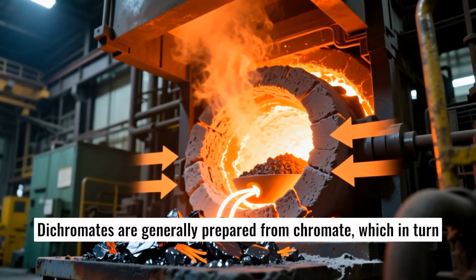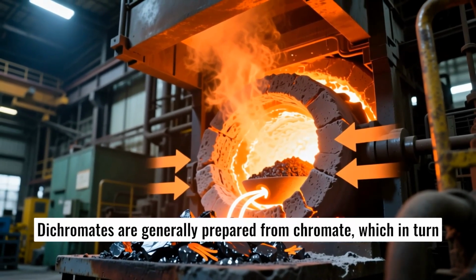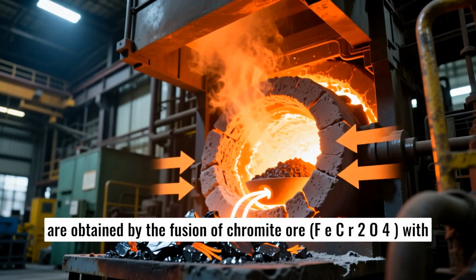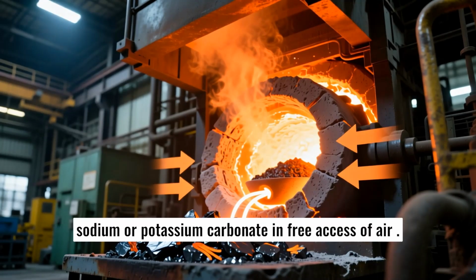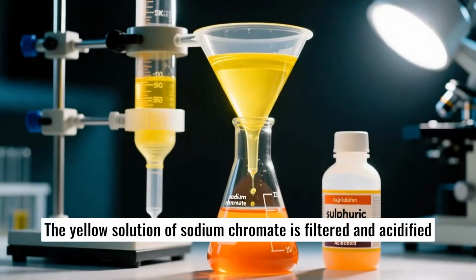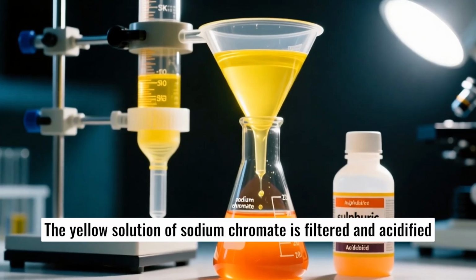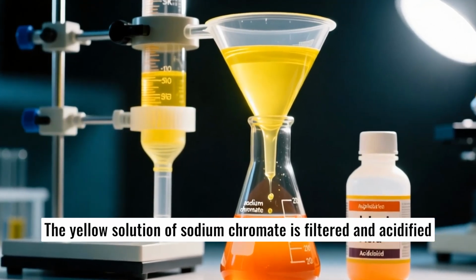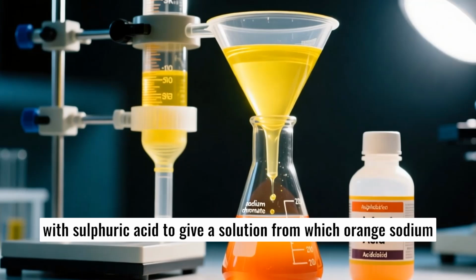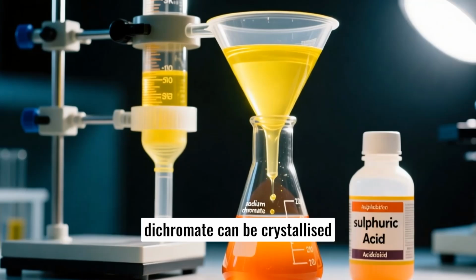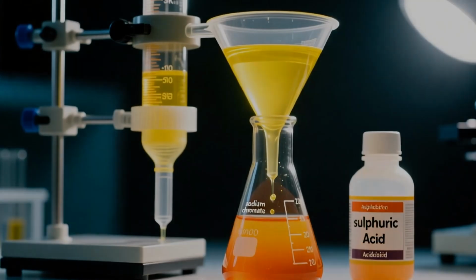Dichromates are generally prepared from chromates, which in turn are obtained by the fusion of chromite, FeCr2O4, with sodium or potassium carbonate in free access of air. The yellow solution of sodium chromate is filtered and acidified with sulfuric acid to give a solution from which orange sodium dichromate can be crystallized.